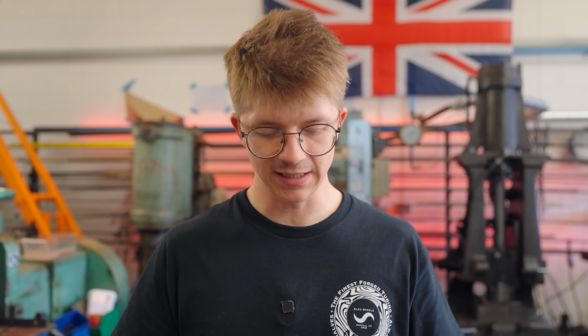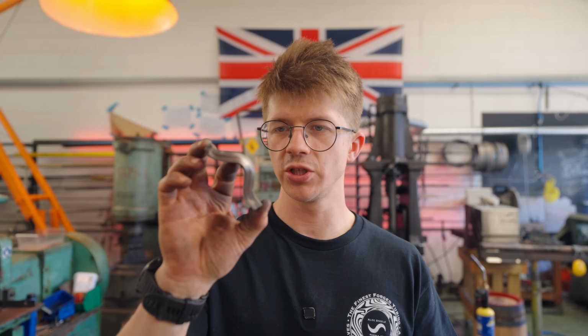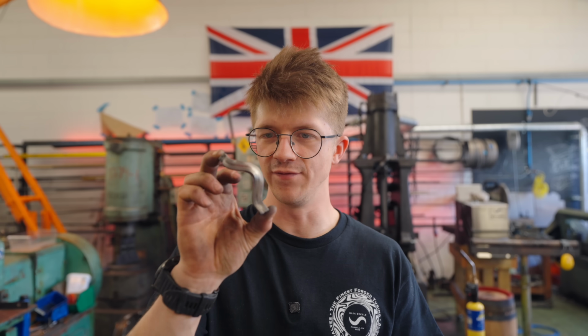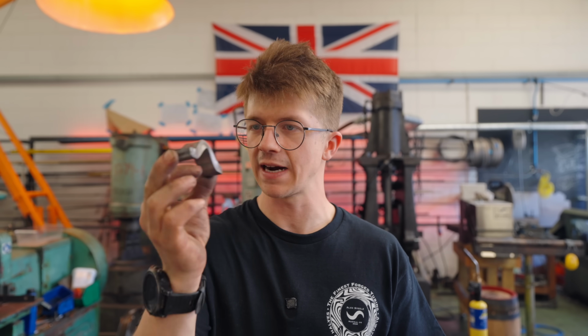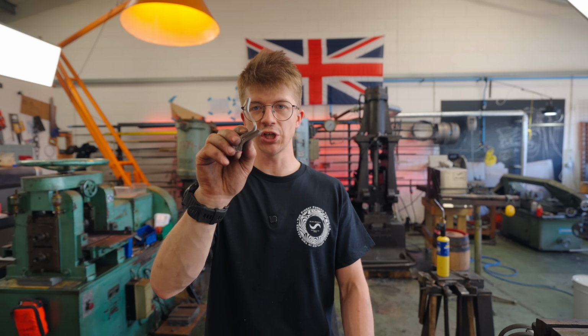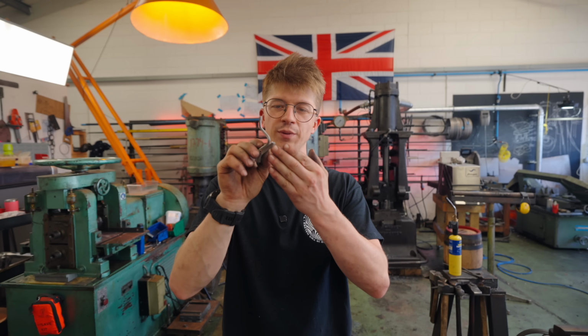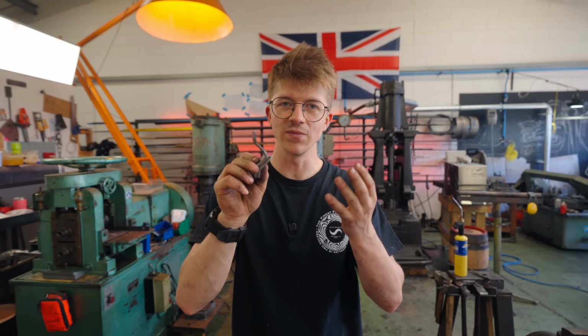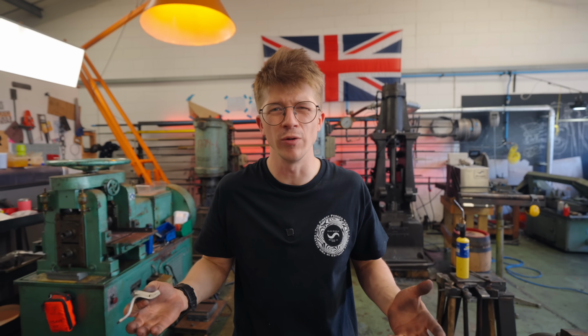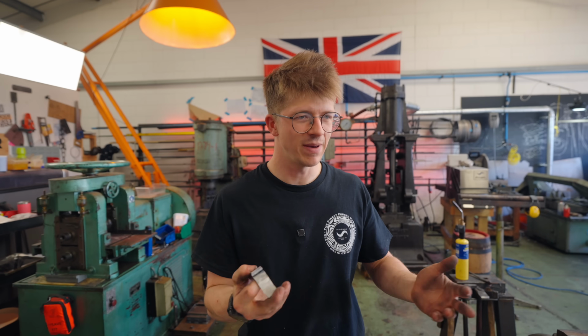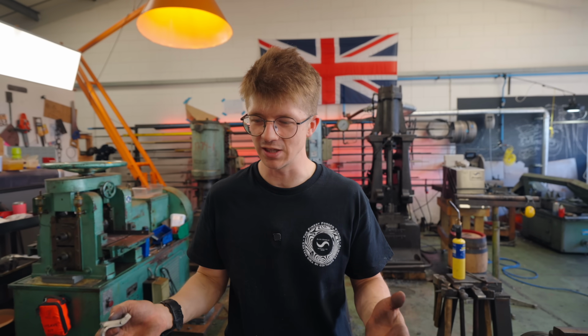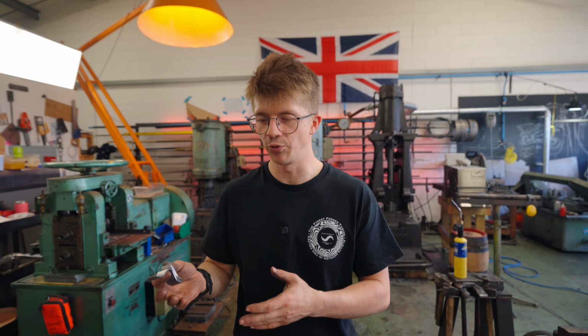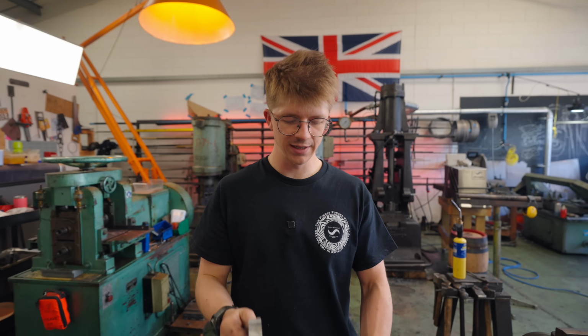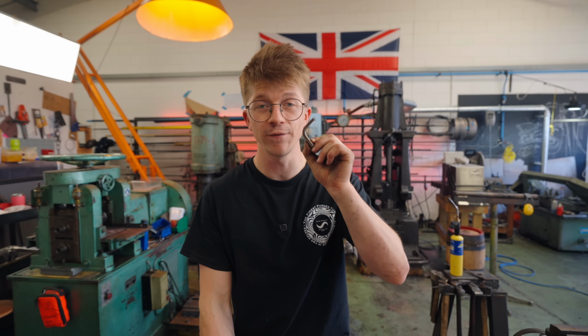What's very exciting about this test is we have shown that the titanium to steel bond can be very, very good, especially in its unhardened state. The fact that that didn't separate is remarkable. We have shown that it's likely not going to perform as well as just a bit of steel. We kind of know that, right? That's why katanas are made of steel and they're not made of titanium with steel. The characteristics of steel suit a sword really, really well. But what I'm thrilled that we've learned is that it is possible to forge it.